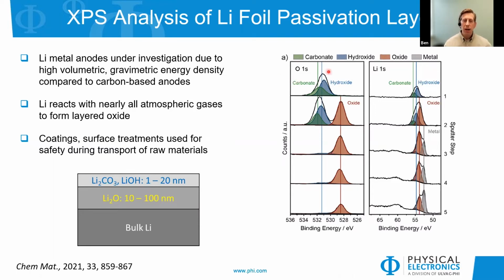And we see essentially carbonate and hydroxide species in both the oxygen and lithium. But we do a little bit of sputtering, and then we see that there are some differences in the states, and we actually get more of a lithium 2 oxide state showing up. And then with further cleaning, we eventually get more to a pure oxide, with a little bit of the oxygen showing an oxide state. With the lithium, we also do see the eventual emergence of a peak at low energy, which would constitute a metal. But again, this is typically short-lived, because even the residual gas in the chamber can cause it to reoxidize pretty quickly. And so what we're looking at maybe are different coatings or surface treatments that we can put on the lithium foil to passivate this in a controlled way.